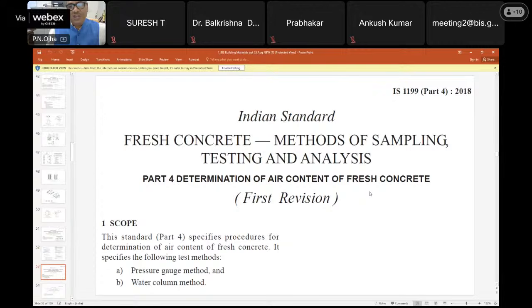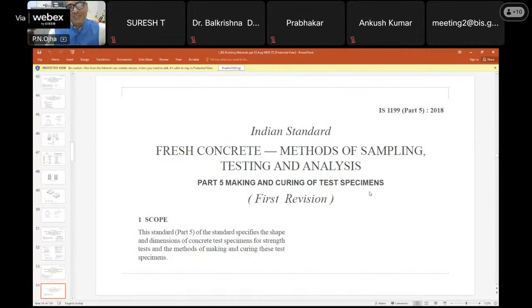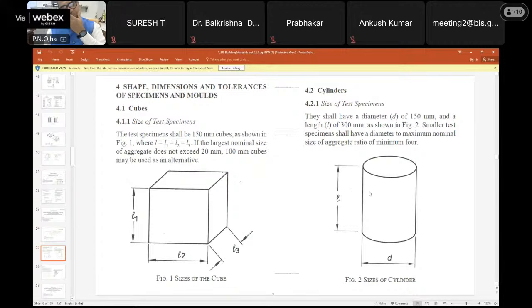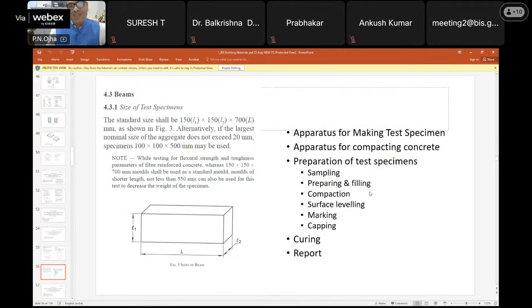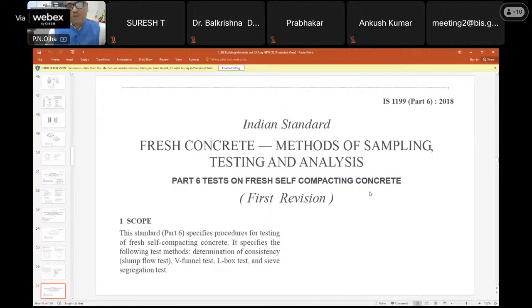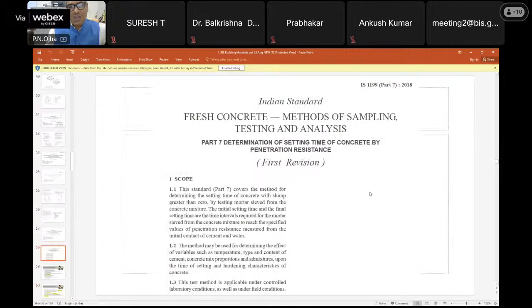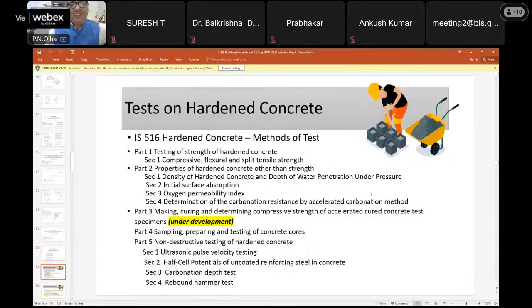Then determination of density, and how to determine density. These are the formulas. Then determination of air content, where two methods are mentioned, the pressure gauge method and the water column method. You can see the equipment. Then making and curing of test specimens in part 5: how the cube specimens are made, how the cylinder specimens are made, how the curing is done for the specimens. These are very, very important while making any concrete structure. Then tests on fresh self-compacting concrete, various tests, then setting time of concrete, penetration resistance, and then tests of hardened concrete.